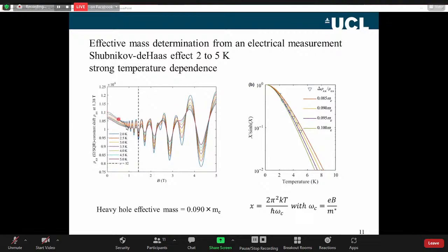As we heat the device up, you can see two things that happen. First of all, we lose the quantum oscillations. The quantum oscillations are thermally damped. The second point is that the resistivity is dropping. We heated the device up by only 3 Kelvin. Huge change in device resistance. So that was something, we got a very, very clear magnetic oscillation. The device itself was very, very temperature sensitive.